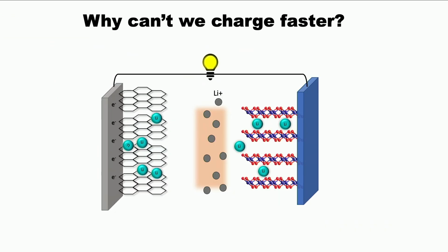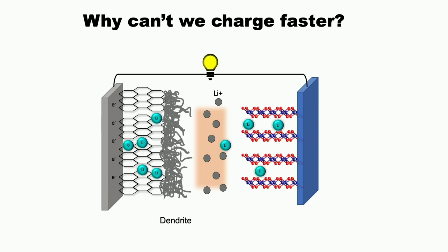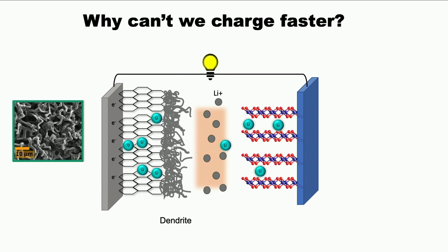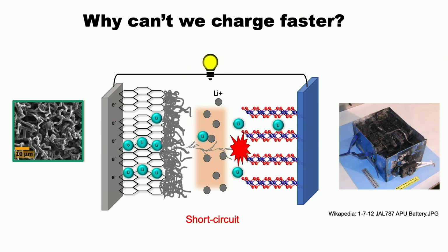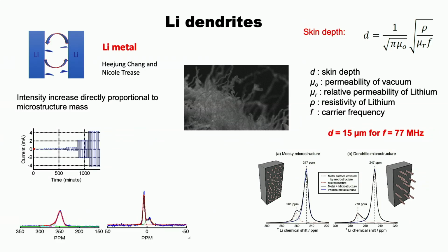The other thing, which we like from an experimental point of view, is that if you charge too fast, instead of intercalating nicely into graphite, you form these dendrites. These dendrites look very beautiful, but they have also caused incidents like the Dreamliner plane, which was at least thought to be associated with a dendrite incident. So we can do NMR and track our dendrites by NMR. The thing about NMR is that it only has a certain depth. It can go through a metal called the skin depth, and that allows us to track the dendrites being formed. So this is the dendrites forming. This is the passivating SEI forming on top that we can track.